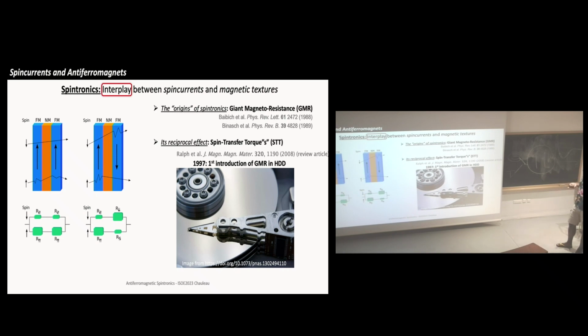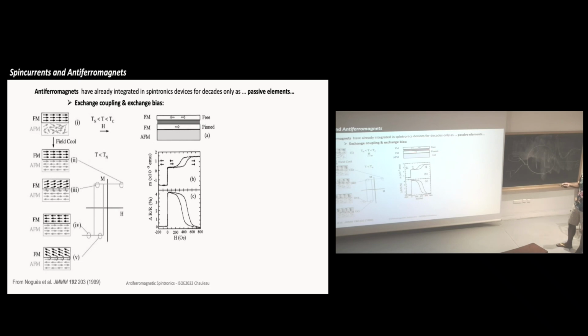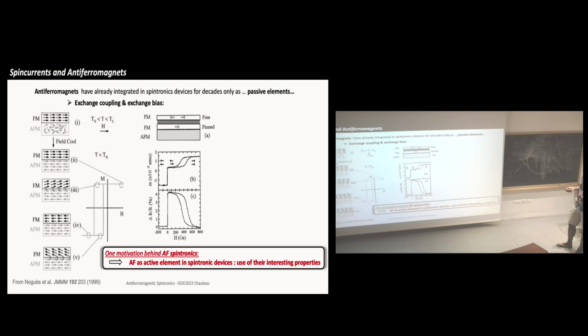Okay, but the thing you need to know is that antiferromagnets were already used at that time. But they were used as passive elements, basically to pin one of the ferromagnetic layers using exchange bias. But of course, the goal of antiferromagnetic spintronics is to wonder if we could use antiferromagnets as active spintronic elements in these devices, and especially to use their interesting dynamical properties. And then the first paper, I think this is the pioneer paper, I think this is the first one.